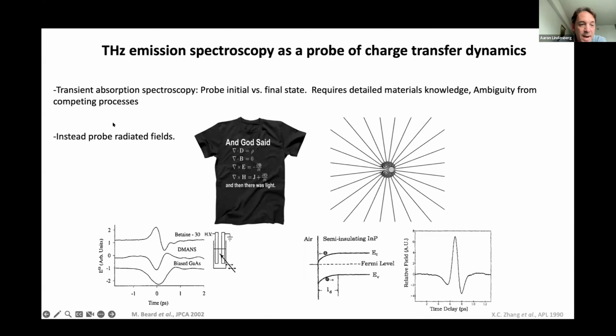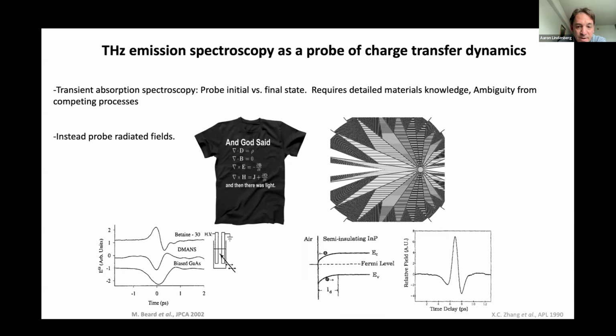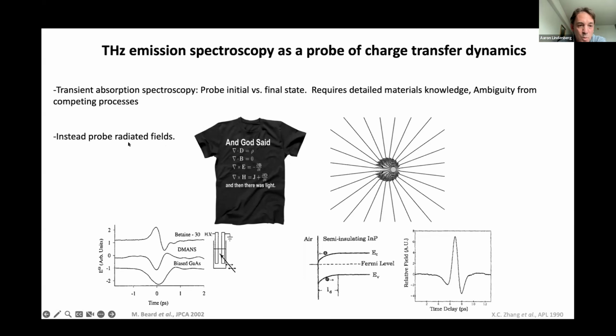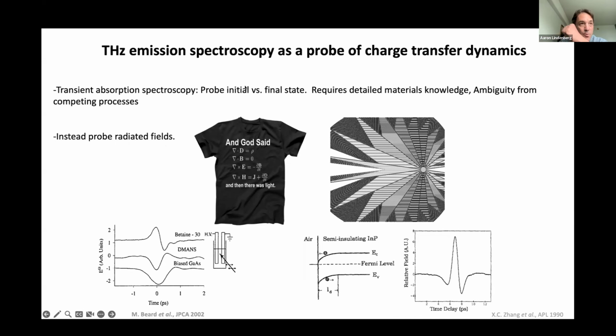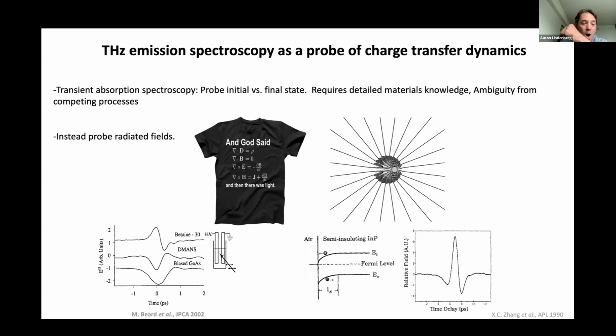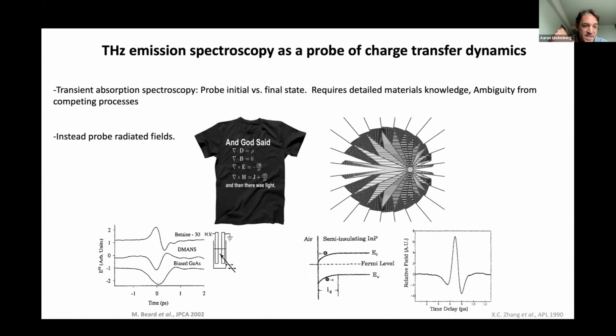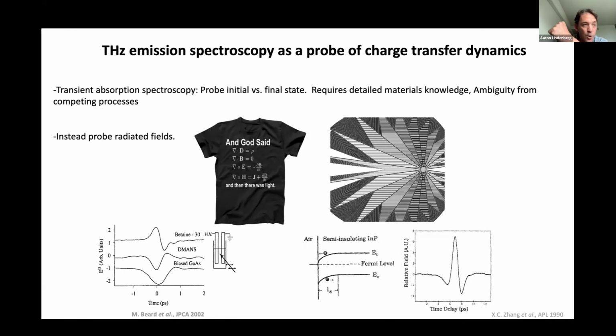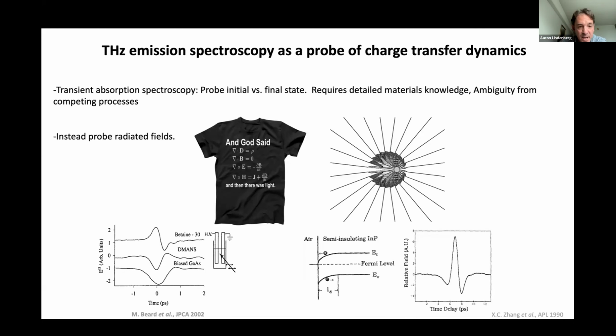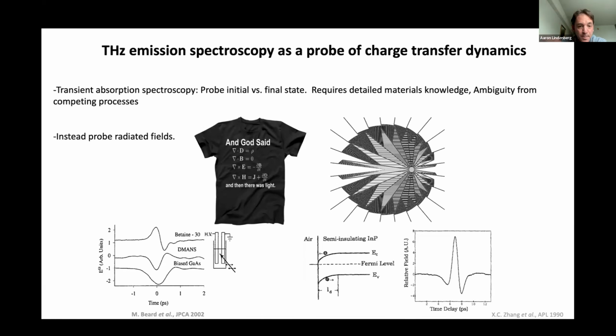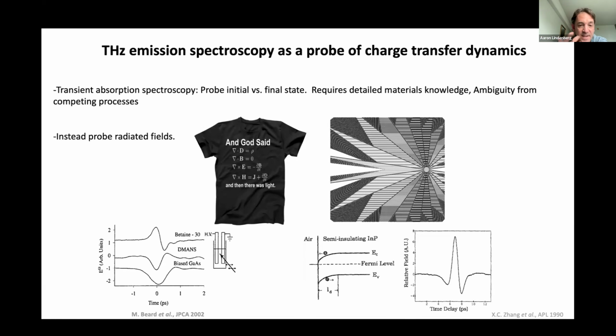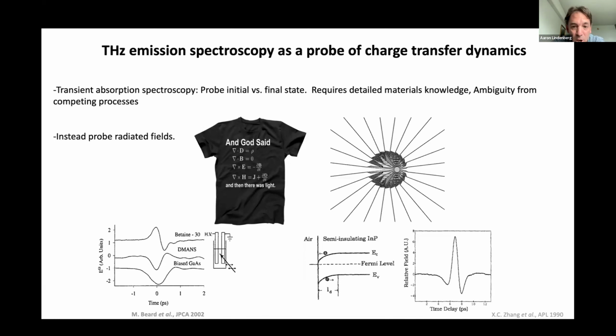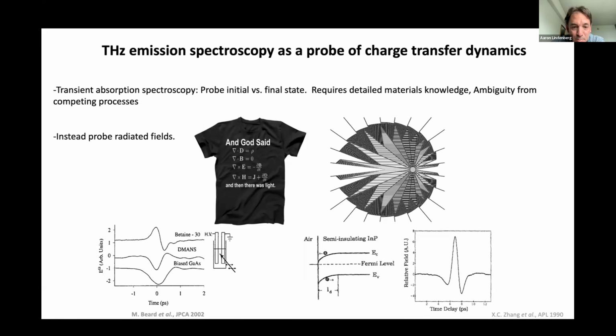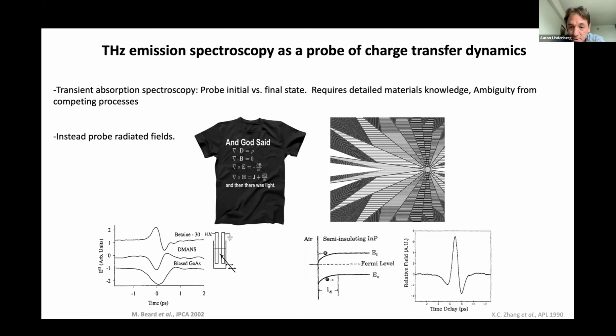And so we started thinking about more direct probes. The first example I'll very briefly mention is experiments where, instead of trying to probe the band structure, we try to zoom in and watch the motion of the charges themselves across the interface. And of course, when this interlayer exciton is formed, when charges jump across the interface, this is a time-dependent current. And we all know, if you're at Argonne, that this is the principle that underlies how a synchrotron works.